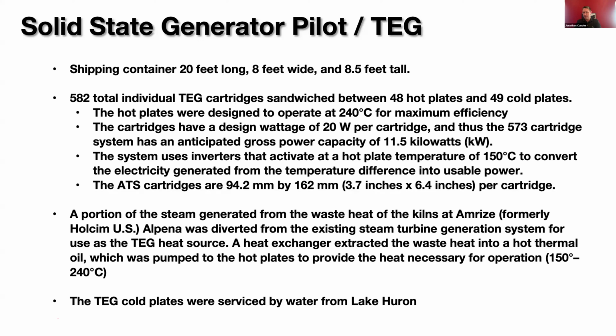We used a portion of the waste heat from the kilns at the Amrise facility, formerly Holcim U.S.. Amrise provided us this existing steam. We then turned that into a transfer oil that was able to be pumped across our hot plates for operation at 150 to 240. Luckily, we had Lake Huron right by, so we used that for the cold water source in the cold plates. Next slide, please.